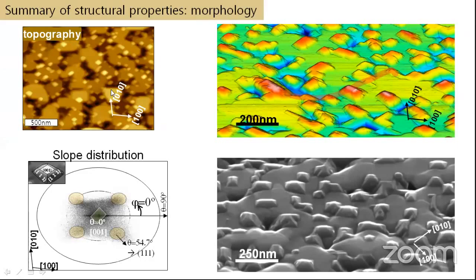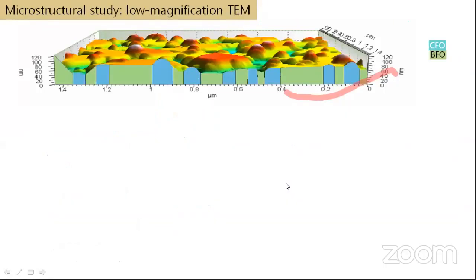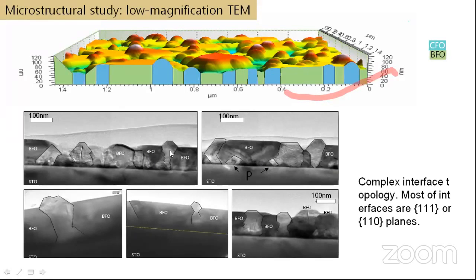This is the AFM image. It shows very nice nanorods. This is the spinel rod on a perovskite matrix. So these are all nanorods on a perovskite matrix. This is the low resolution TEM image. The cross section shows that the interface is not as clean as we expected. In the first slide I showed a cartoon, so I think we can annotate.